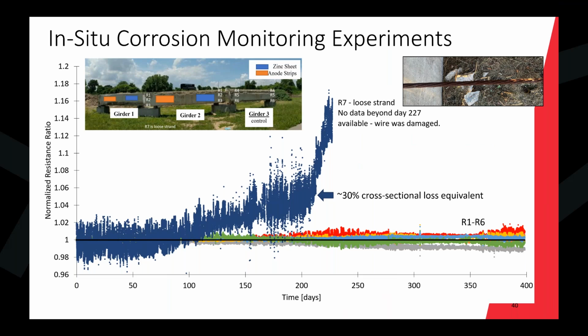But you can see the time span if you just had a strand completely exposed, that it's going to corrode to the point of going in 250 days. And the 6 strands that we were monitoring are all the other colors on this plot, and you can see that they all stayed pretty close to home, which just means that we weren't getting any real active corrosion, even though we were salting these beams. We had picked all of these as intentionally embedded, so this is not much of a surprise.